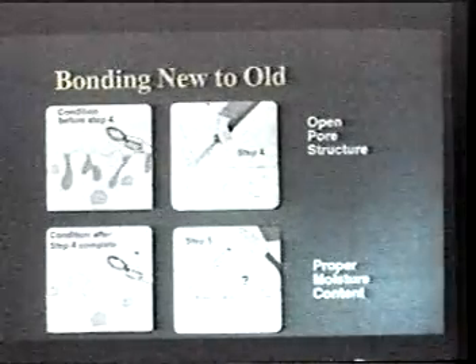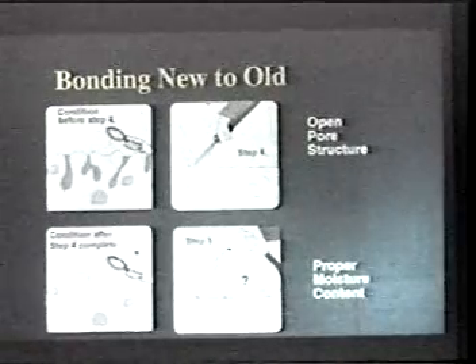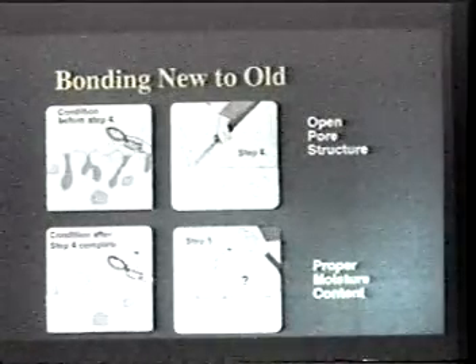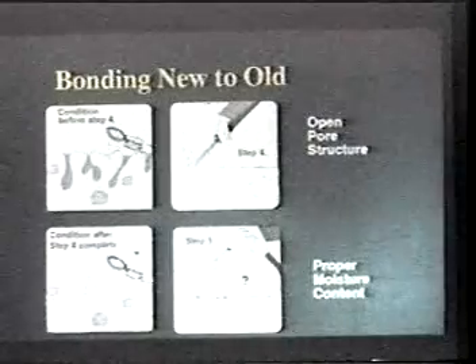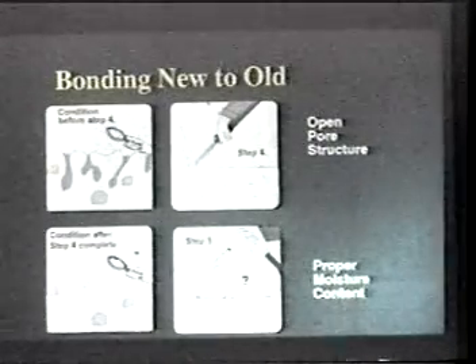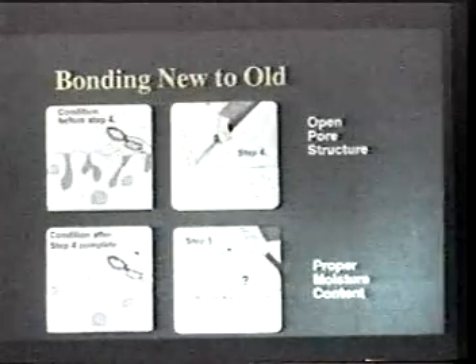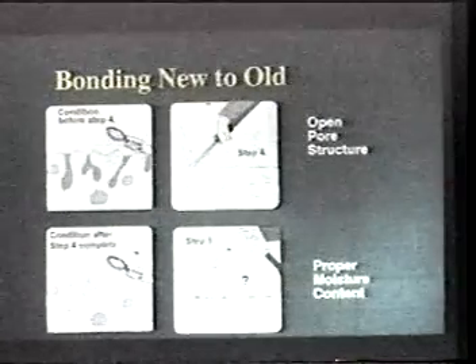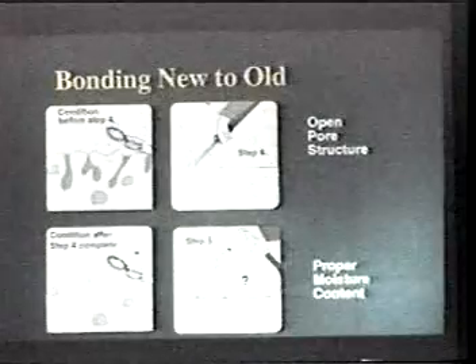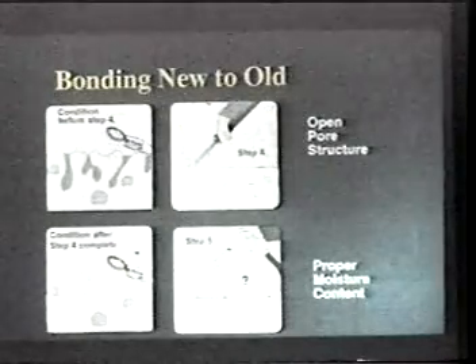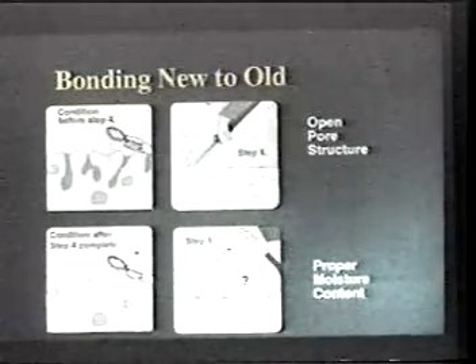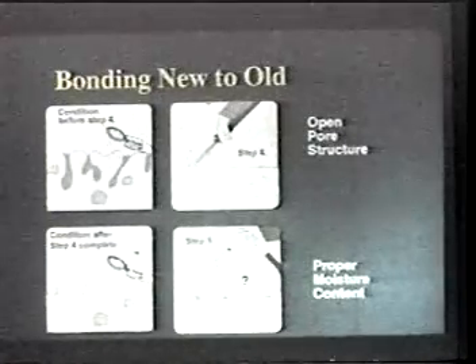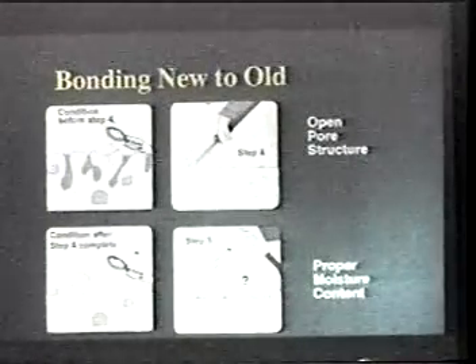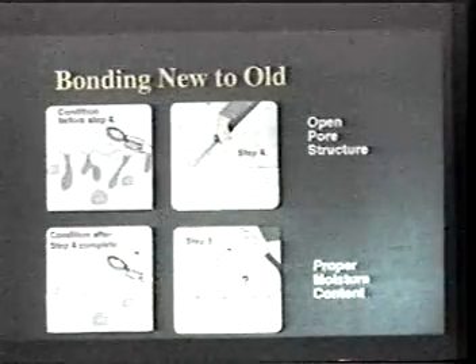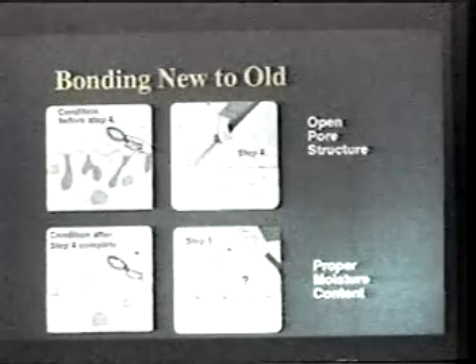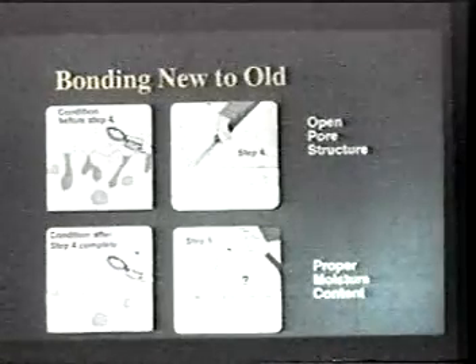Now, another issue which I have, look at the last one, proper moisture content. We have a very good, very conservative approach. We are always recommending SSD condition to be on a safe side, which is actually saturated surface dry condition. But is it the best, and I'm going to finish with this, the best moisture condition before you are applying? Of course it is not. It is probably the safest, but not the best.